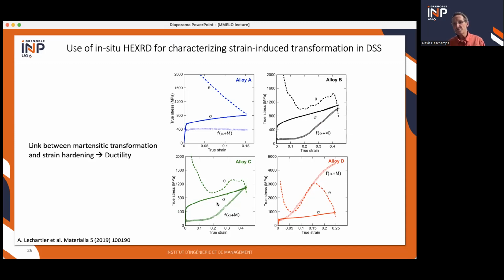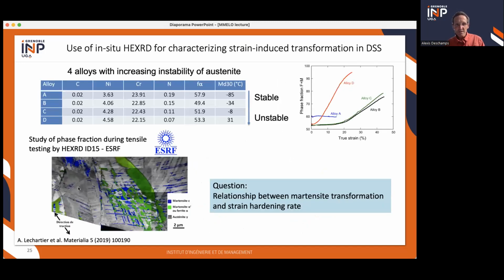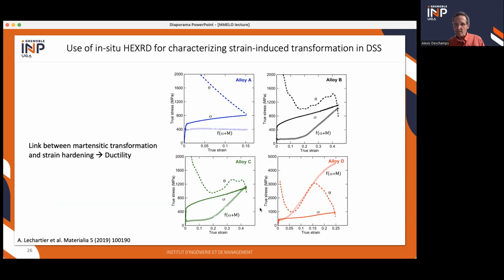In the two alloys which are intermediate, actually mastering the kinetics of the martensitic transformation makes it possible. Since it's a bit slower, it happens later on, only after 20% strain. And this is because it's preceded by epsilon martensite formation before you do the actual alpha prime transformation at the intersection between the two series of epsilon martensite. So you're able to keep the strain hardening rate just above the stress for very, very long, and then go to about 45% of deformation before failure.